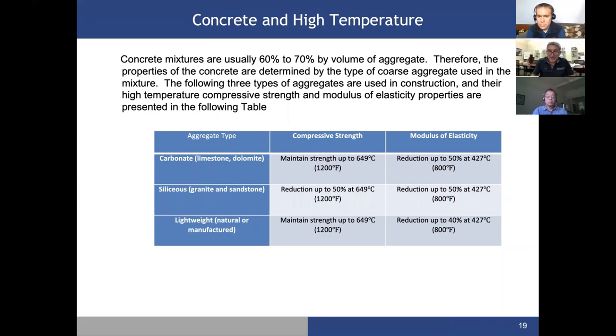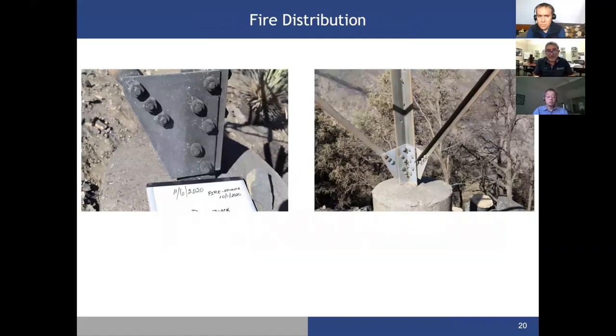So let's look at some examples. The photograph on the left side shows that this site is exposed to wildfire. You can see by discoloration on the load-bearing member and also on the concrete. On the right-hand side of this tower, you can see evidence of very mild exposure to high temperature. Both the concrete and galvanized steel look completely normal.